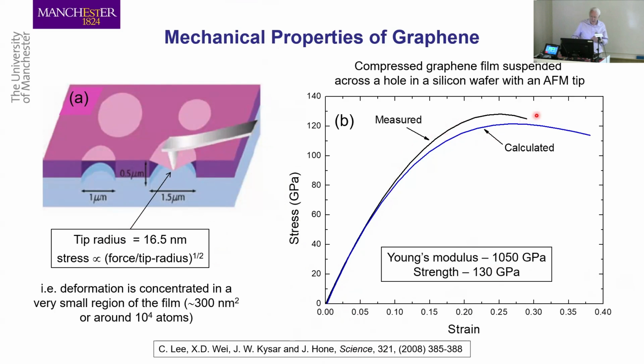There's also a calculated one in another paper. And the initial slope of that gives a modulus of 1,050 gigapascals. That is 4 times steel. No, 5 times steel. And they also measured this most enormous strength of 130 gigapascals. Absolutely enormous strength. And so the question is, are these two measurements realistic, or can we use them in other applications?